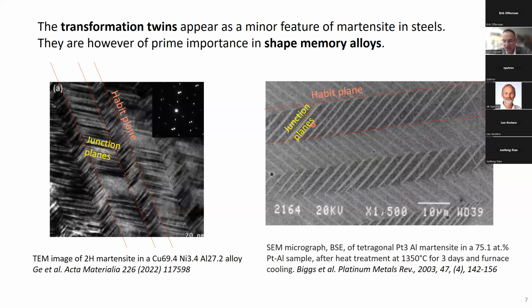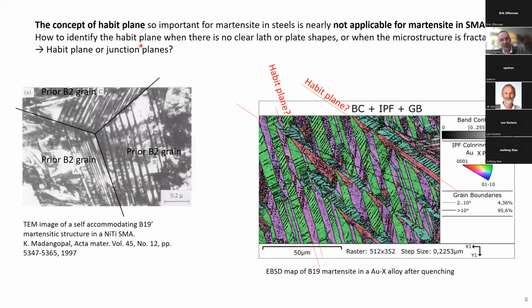The junction plane is very important for shape memory alloy. On the contrary, the concept of habit planes is sometimes very difficult to define for shape memory alloys. For example, here it's a nitinol, a nickel titanium shape memory alloy, in which we have the prior parent grains, cubic B2 grains, and we do not really see a plate. We see the variants here with the junction planes, but we do not see planes.